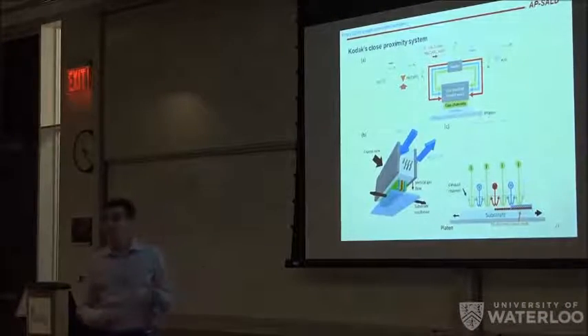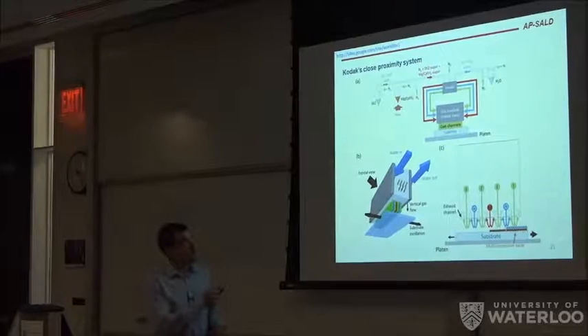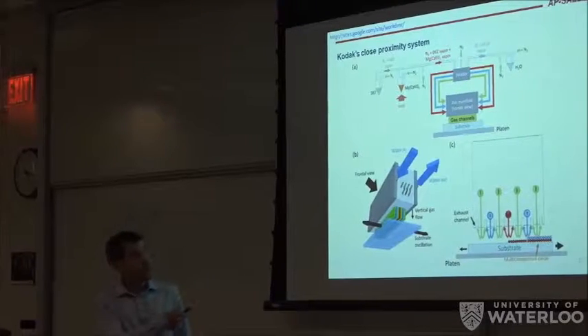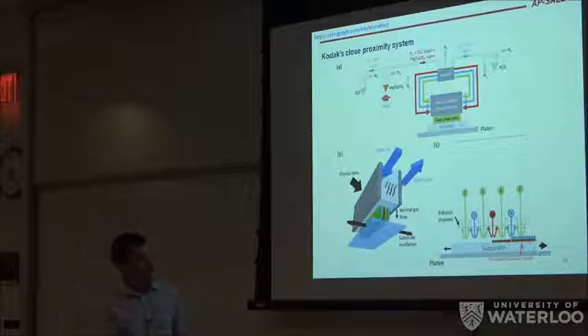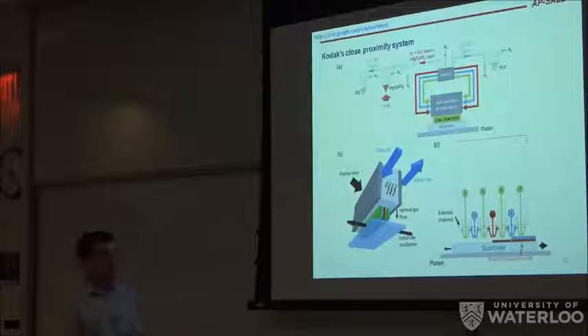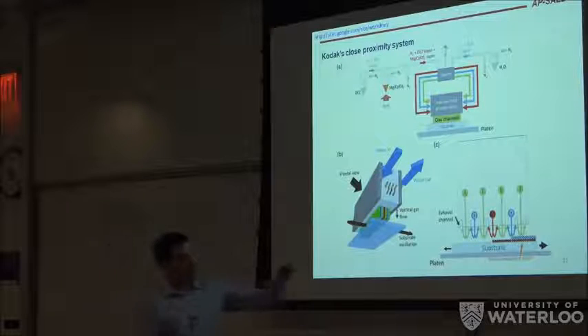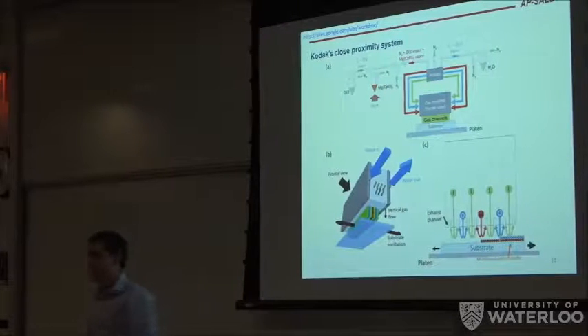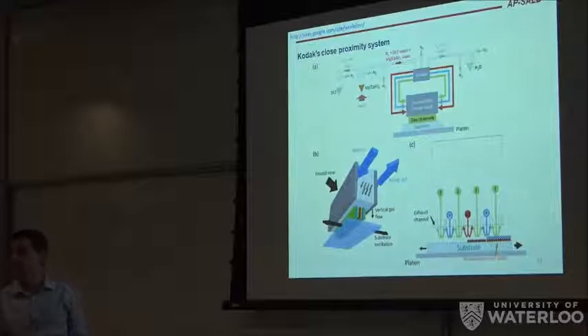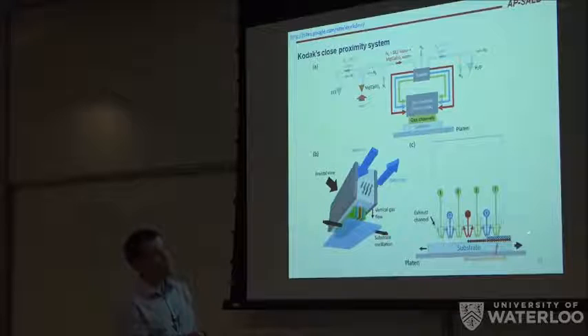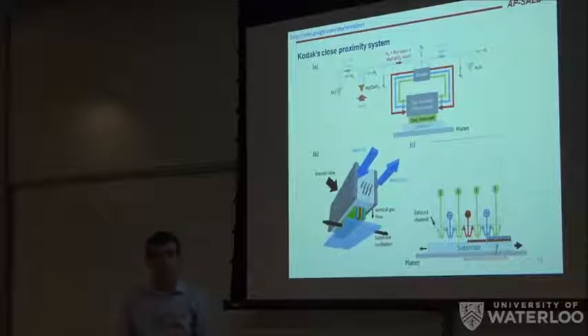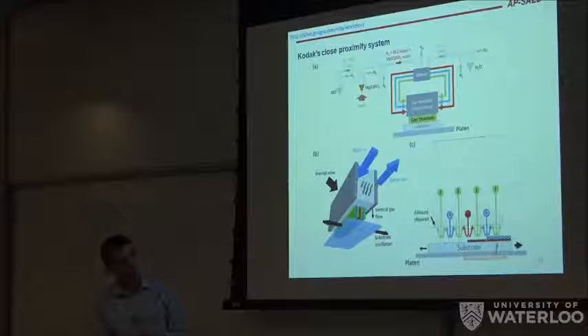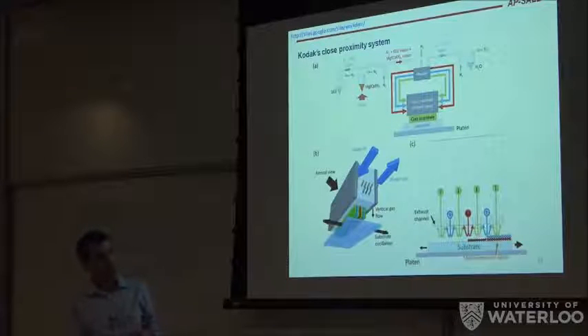So this is schematically how a Spatial ALD reactor works. We have bubblers containing different precursors, which should be volatile, and then we flow nitrogen through the precursors, which carries the vapor of the precursor to the manifold head. And there is where we manage to separate them along parallel channels. And then by getting the substrate very close to the head, at 150 microns, we manage to prevent mixing from the different precursors, and then we just need to scan this substrate back and forth to replicate the conventional ALD cycles. In here, the sample would be exposed to the metal precursor, then it would be swept by this nitrogen flow, and then, again, it would react with the oxygen flow.